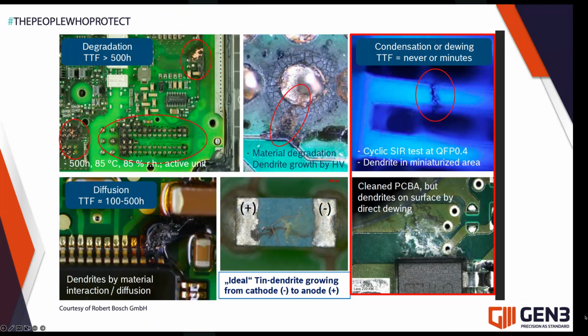The top right picture shows a dendrite which is grown under a condensing condition. And here we obviously can see the dendrite, but in condensation testing or dewing testing, it will find a failure very quickly. But if it doesn't find a failure, it will never fail. So it's a much faster test.